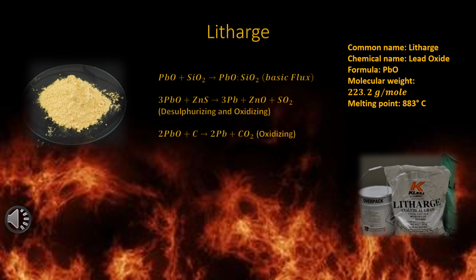It is also used to form the slag with the acidic flux, which is the silica and borax. The result is the formation of the lead silicates. The melting temperatures are lower than the base silicates. It is for this reason that the lead oxide is always or almost always added to every crucible fusion.